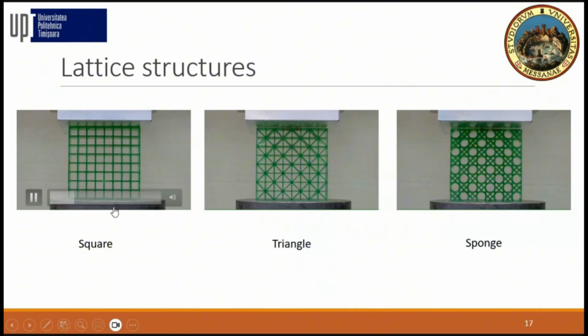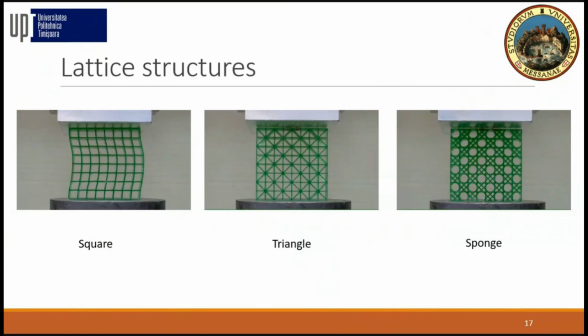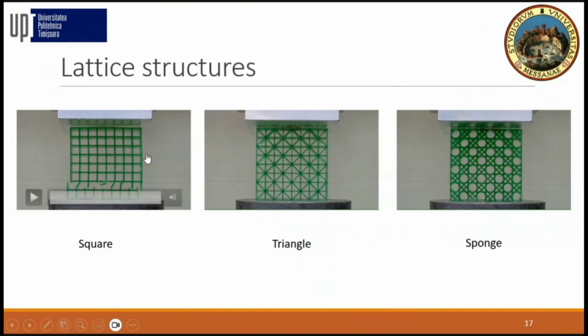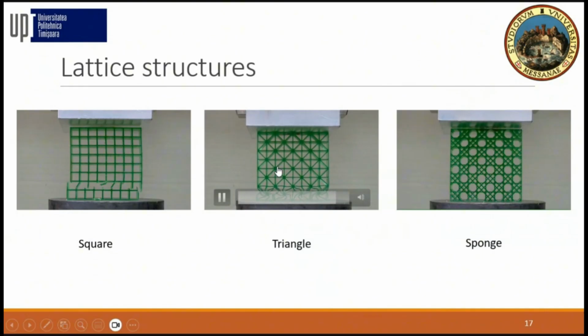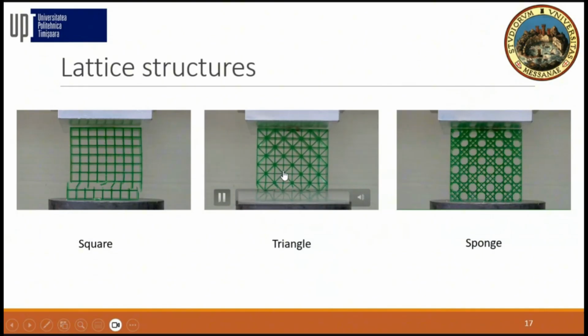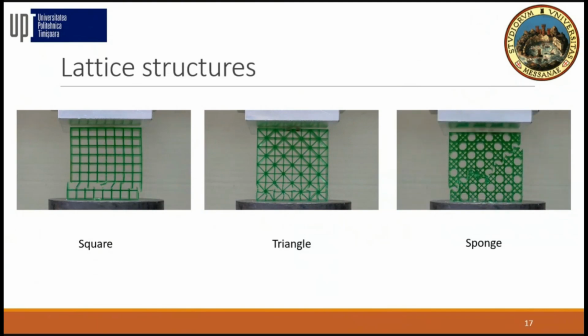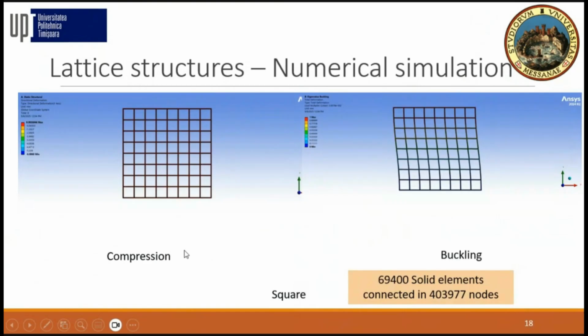It's okay now. So for the rectangular structure, we have buckling and then failure of the, let's say, lower layer. For the triangular, we have a local buckling on the edge and then fracture. For the sponge structure, we have no buckling at all, and the failure is at a 45 degree band. So having these experimental results, we move to try to simulate the behavior.